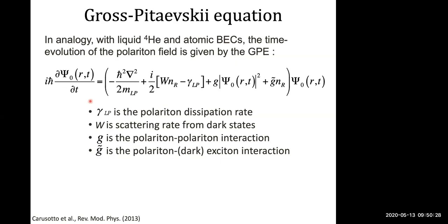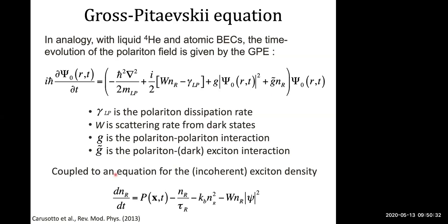So this Gross-Pitaevskii equation is combined with a simple rate equation which describes the occupancy of our dark states. So these dark states are populated by a laser pump. They decay with some lifetime. We might have bimolecular annihilation, so you can include that. And this is scattering from the dark states to the condensate.